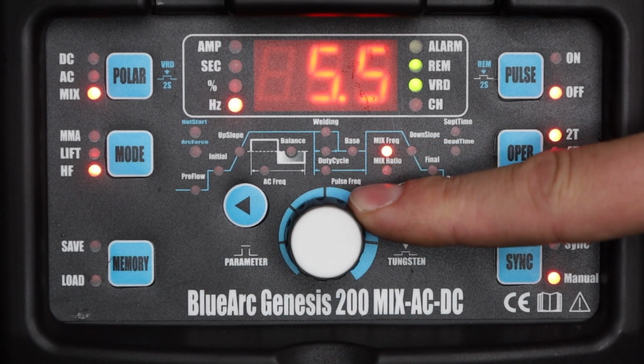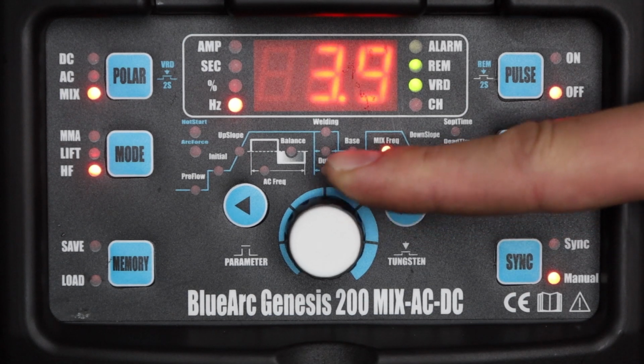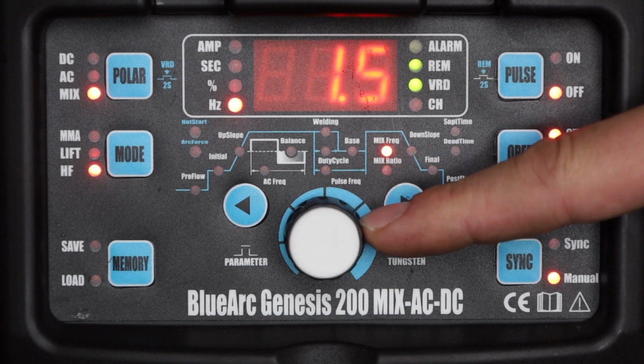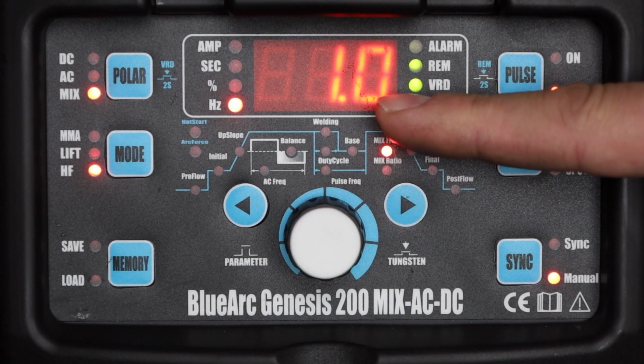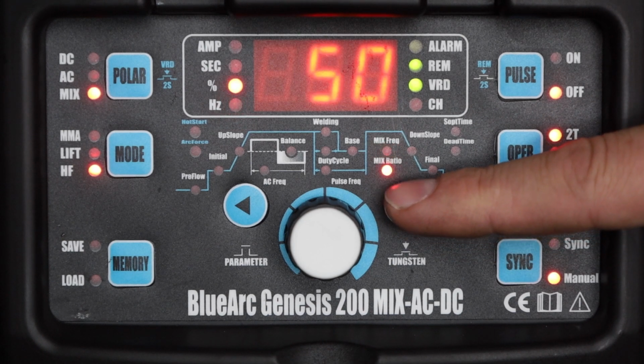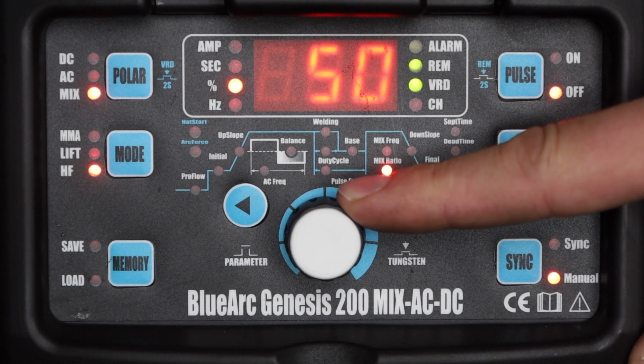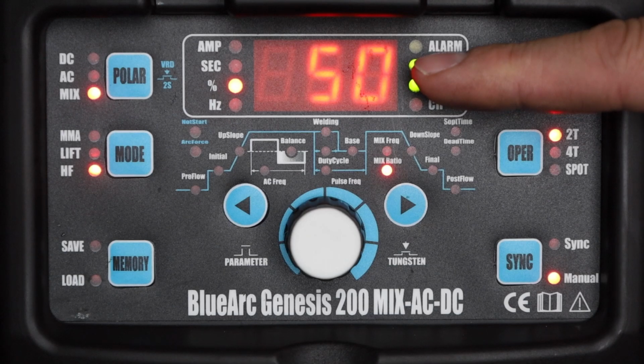Mix frequency, that's how many times per second it will change back and forth between AC and DC. I'll set it at 1.5 Hz so we can see what's going on. The mix ratio here is the percentage of time that is on DC versus AC. I'm going to leave that at 50%. Now you can see as I weld here, it goes to AC and etches and you have that buzz, and then DC just drives additional heat and penetration down into the material.